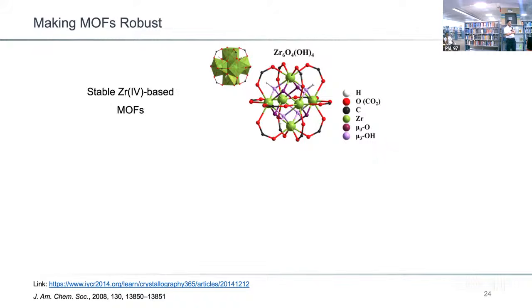But in this particular example, what they showed is that if you choose a specific metal ion, which is zirconium in the periodic table, the structures that form out of this unit are actually very stable. They are even stable to different pH conditions. They're even stable to thermal changes. So they can be stable up to even 300 or 400 degrees Celsius. So this has been regarded as one of the key milestones in the development of MOFs.